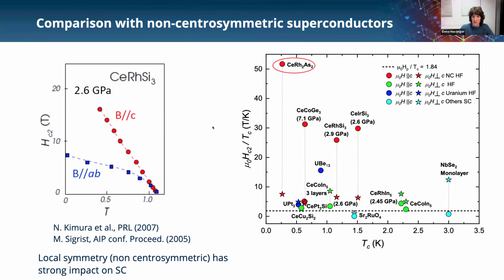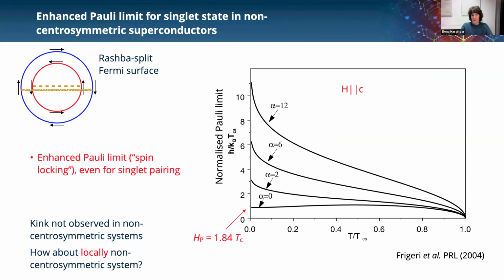So this makes us believe that the local non-centrosymmetry and the Rashba spin-orbit coupling plays a fundamental role in this material to explain the phase diagram. Okay, and just to give you the physics behind it, in non-centrosymmetric materials, this has been calculated. So you have a Rashba spin-split Fermi surface where spins are locked to the momentum as shown here. And then only certain types of Cooper pairing remain when you turn on the Rashba spin-orbit coupling.